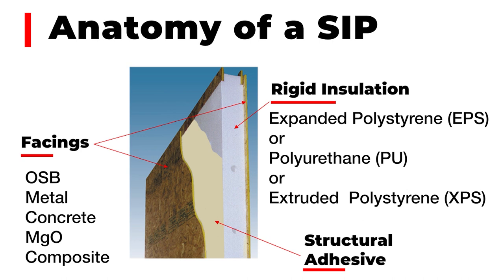Urethane is also used — it's a poured polyurethane, not sprayed, poured to fill the void and create the core. The structural adhesives used are no different from those familiar from LSL, glue-lams, and I-joists — typically a moisture-cured urethane adhesive that binds it all together. It goes into a press, and I'll show photos of that shortly. XPS works well in floors, though when we have a diaphragm and it's subjected to impact, diaphragms tend to transmit sound.